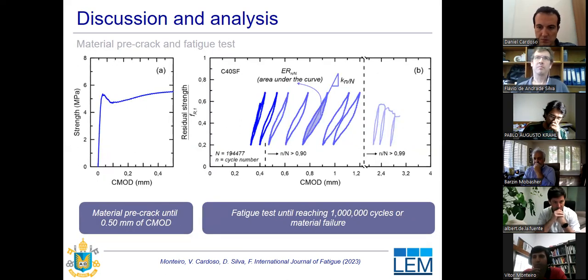The next step was evaluating the material degradation along the fatigue life. So we evaluated the material degradation in terms of stiffness and dissipated energy along the cycles. The stiffness was calculated as the slope of each of the cycles recorded, and the energy dissipated as the area inside each hysteresis loop.